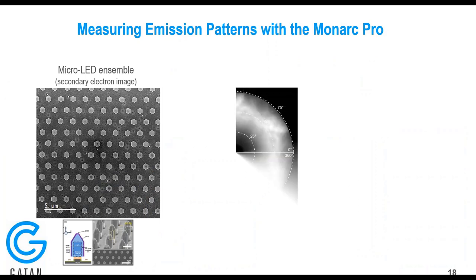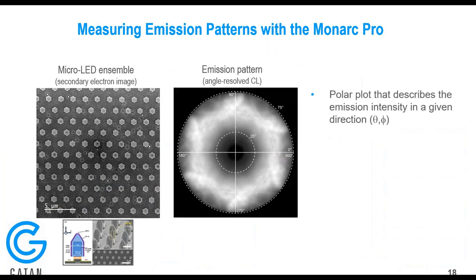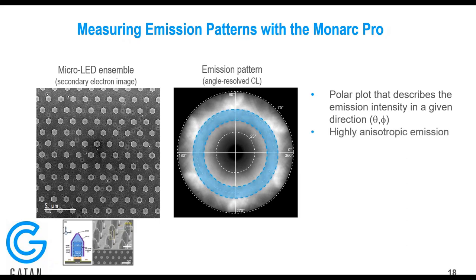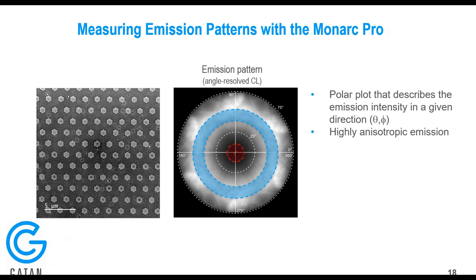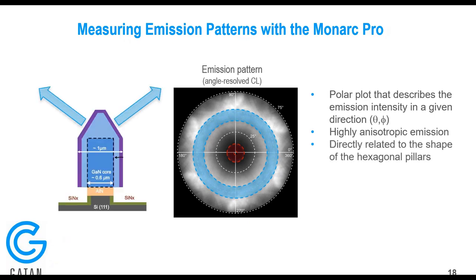So looking at the ensemble, as opposed to a single pillar, we can find the emission pattern through angle resolved CL. So we can tell, in the array format, what angle the light is coming off at. And so again, the polar plot is describing emission intensity in a given direction, and it's telling us where the light is coming out, but not at what wavelengths. What we can see in that pattern is that we have highly anisotropic emission, which means we have directions that are selective for emission. We have a strong emission towards the outside, which matches the surface of the pillars and the angle that they have with the surface. And then there's a weak emission coming straight out towards a viewer.